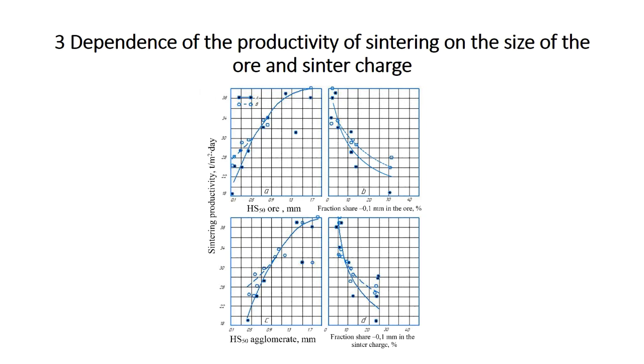In Figure 3, b and d, it is clearly seen that with an increase in the fraction of -0.1 mm, productivity decreases. The difference is again noticeable for ores A and B in the area of fine fractions, and for ore starting with a fraction of minus 0.1 mm 5 wt%, and for the entire charge starting with a fraction of minus 0.1 mm 7 wt%. These differences can also be explained by the different lumpiness of the ore.